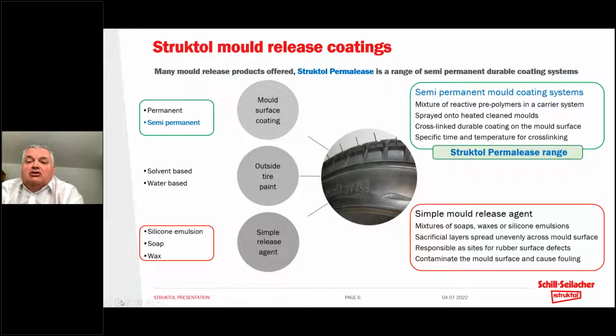Later on, and still today, silicone emulsions are quite widely used in order to provide that lubrication and break the surface tack or adhesion, if you like, between the rubber and the mold substrate. All of these simple release agents could be considered as sacrificial layers, and that means that they're not really bonded to the mold surface. They spread relatively unevenly across the mold surface and provide some kind of lubrication and release site. However, they transfer quite often to the rubber article and need to be reapplied very frequently. And as such, they're also responsible for the buildup of mold fouling. Quite often, the surfactants or the dispersing systems used in these simple products contribute to mold fouling by virtue of the fact that they also degrade during the high temperature used for molding.